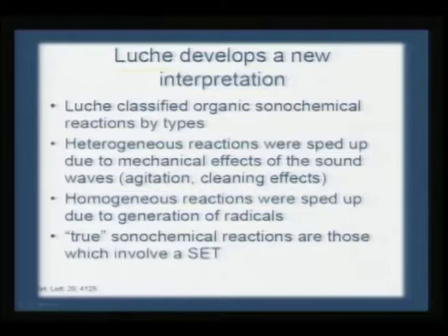Actually it was Luche who did several studies using solvents, and he developed a new interpretation. What he said was there are types of organic sonochemical reactions. One type is heterogeneous reactions, which were sped up due to mechanical effects of the ultrasound waves. As I told you, if you use a metal catalyst, then you have a variety of influence and faster conversion. Homogeneous reactions were sped up due to generation of radicals. So you can single out two issues, one is the mechanical effect, another is due to radicals.